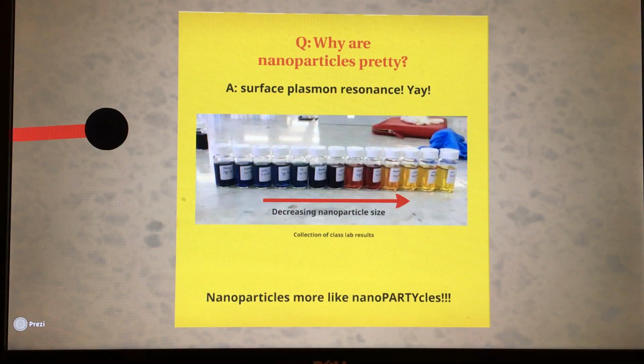The shape and size of nanoparticles can affect the wavelength of light at which surface plasmon resonance occurs. This means that different sized and shaped nanoprisms will absorb different wavelengths of light, thus appearing as different colored solutions. This difference in absorption allows us to estimate the nanoparticle size and shape from the absorption spectra. The larger the nanoparticle, the larger the wavelength of absorption, so the solution will appear a color of higher wavelength. For example, nanoparticles around 100 nanometers in size will absorb colors on the red end of the spectrum, making the solution appear blue-green. Smaller sized particles correspond to smaller wavelengths of absorption, such as blue-greens, resulting in a red appearance.